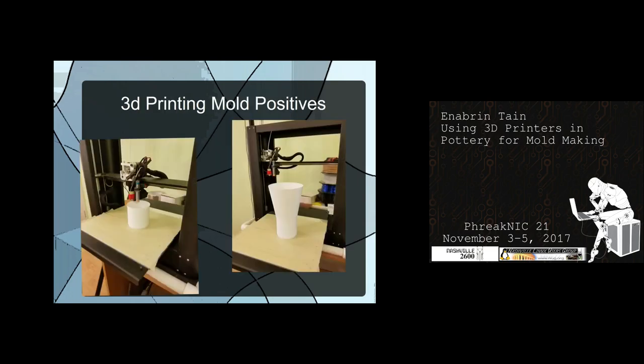Here's a picture of me making a horrible mistake. I designed a cup I wanted to cast, and I used the spiralize function on my 3D printer, so it was exactly one filament's width thick. As soon as it went into the pot of melted wax, it immediately turned to gel. I had to reprint it because it completely fell apart in the wax, and then I had to fish it out of the wax.